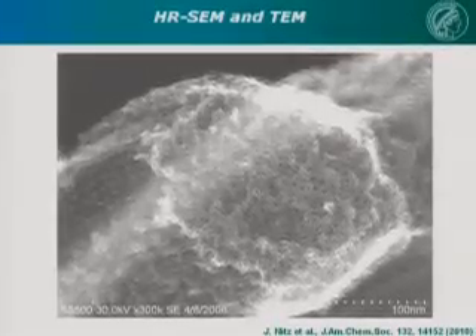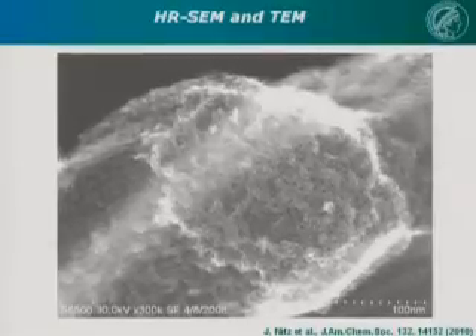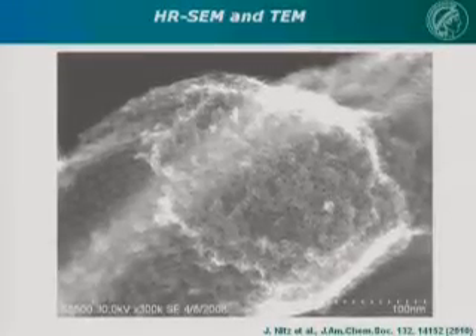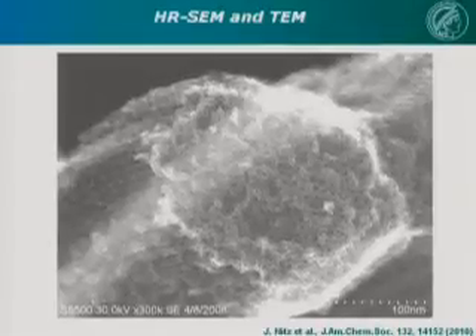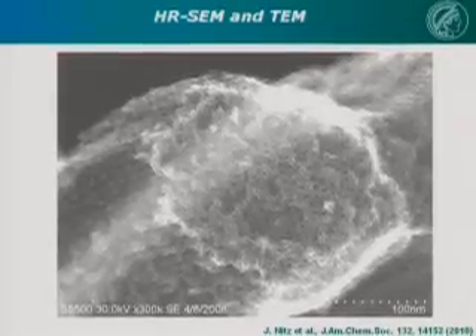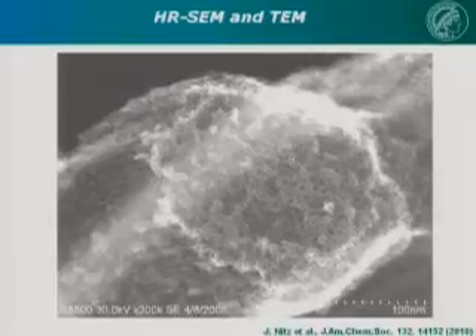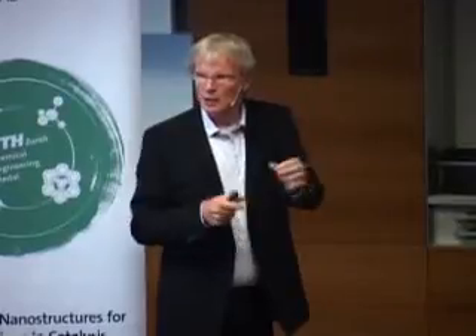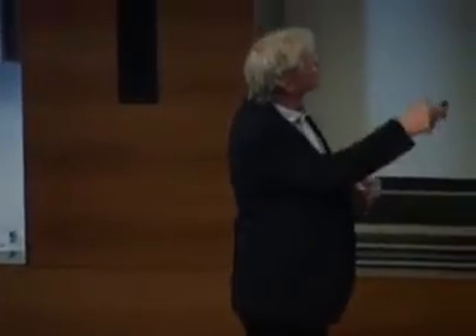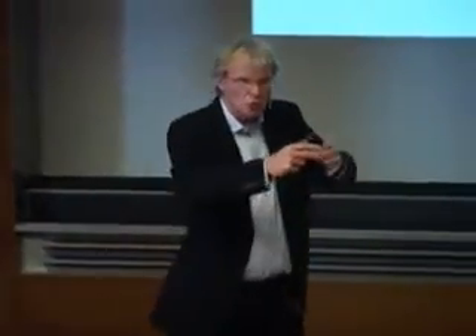I have actually brightened it up to make the pores better visible in this micrograph. And what you see here is actually the carbon tubes extending out from this hexagonal array here. The carbon thickness, the wall thickness, is approximately a nanometer, and the inner diameter of the tubes is approximately 4 nanometers. And since we have placed the iron oxide particles all within the tubes, you basically don't see anything on the outside. Occasionally you find an iron oxide particle on the outside of this carbon arrangement, but in principle, it's all inside the tubes nicely embedded.